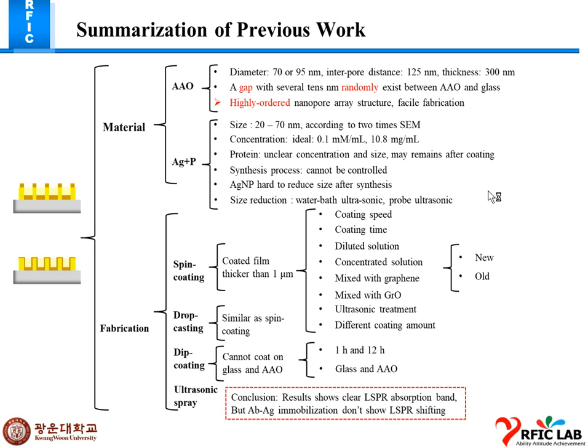The Ag nanoparticle is hard to reduce in size after synthesis because it has protein content, and for the synthesis part we have to use a higher temperature reduction system. So it's impossible to reduce the size in the presence of protein, because if we increase the temperature beyond a specific point, the protein denatures and there is no activity in the sample. For the size reduction, we have used water bath ultrasonic and probe ultrasonic.